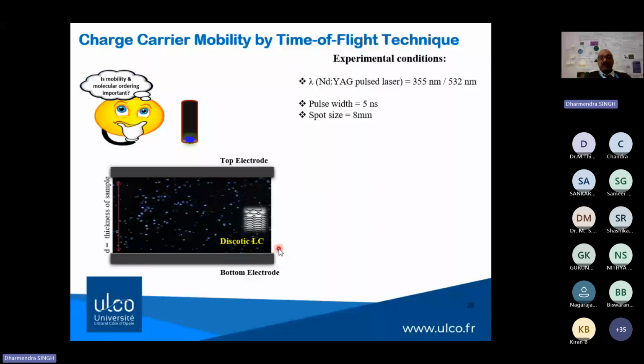So what happens when you irradiate this material with the laser light? This laser light is absorbed within the 10% width of the device by the material, and then what happens? This is the quantum phenomenon: one photon is absorbed by the molecule and it releases one associated exciton. So when this photonic energy is absorbed by the material, it generates excitons. What is an exciton? An exciton is a quantum bound state of an electron and a hole. All of you might know it from quantum mechanics. And the important thing is that these excitons are not stable at room temperature.